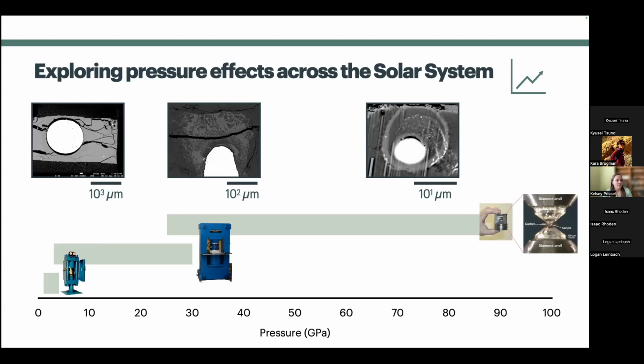As we go to higher pressures, the samples get smaller and smaller. For the diamond anvil cell experiment, we're still able to get a couple of electron microprobe points on our phases of interest to be able to calculate those partitionings. However, if we wanted to study trace elements that require something like laser ablation ICP-MS or some other analytical method, we're now limited by our sample size because we're not necessarily going to be able to put a laser pit and get a clean sampling of our metal in that small experiment.